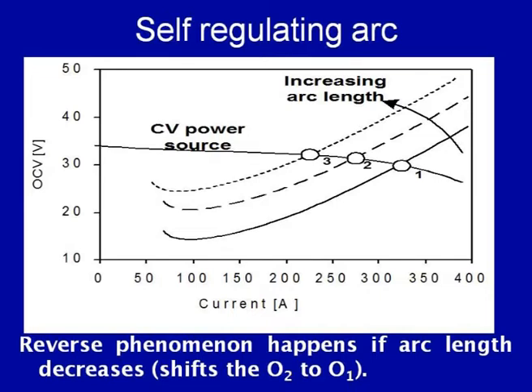The change in operating point is accompanied by a minor increase in the voltage. The minor increase in voltage is associated with a significant reduction in welding current, say from 330 to 270 ampere. So, this reduction in welding current in turn will decrease the melting rate, and if the electrode is fed under the conditions when the melting rate has been reduced, it will help in decreasing the arc length. So, the arc gap is maintained. Whenever there is a change in arc length, it affects the arc voltage and the melting rate, and thereby under constant feed drive conditions it helps to maintain the arc gap.